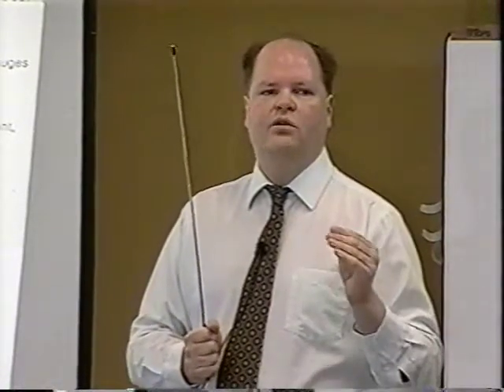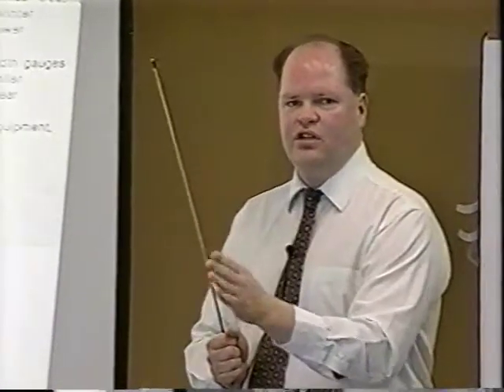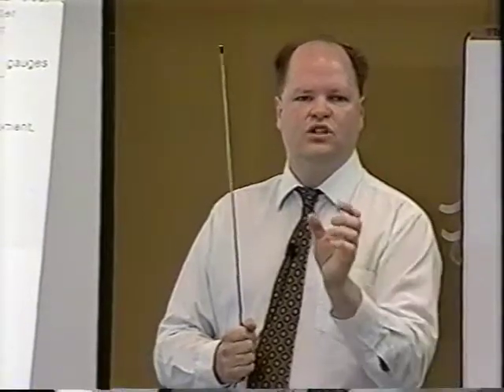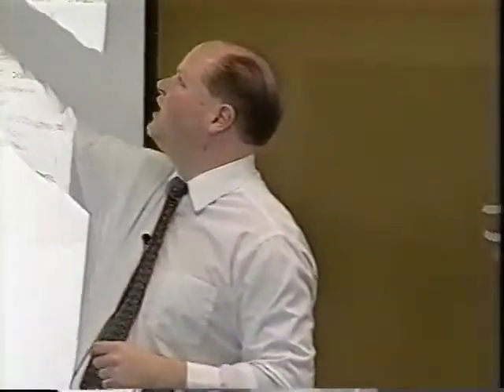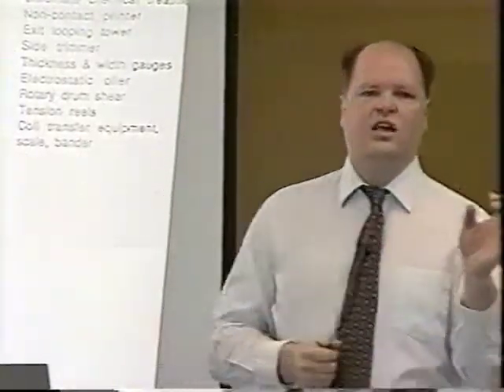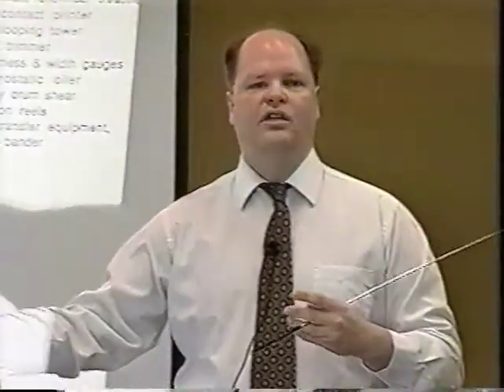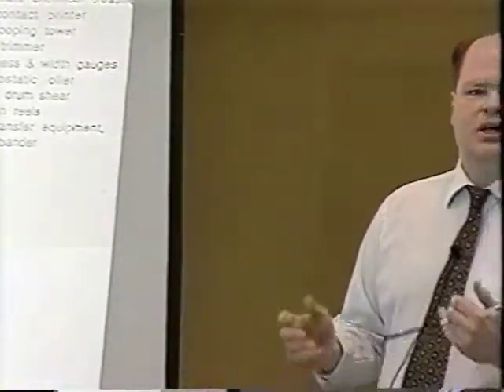So there's a fine line you walk in making galvanneal between under galvannealing and over galvannealing. There's only a small window in there. So that X-ray gauge kind of helps us maintain in that window. So we're not waiting till we get results back from the lab on the powdering test to see, uh-oh, we're really over galvannealing this, we better turn the furnace down. So we can kind of do all that online.